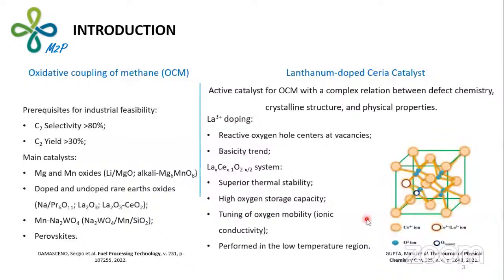The oxidative coupling of methane, the OCM reaction, has some prerequisites for industrial feasibility, such as a C2 selectivity higher than 80% and a C2 yield higher than 30%. In the literature, some catalysts are reported, such as manganese and magnesium oxides, where doping the system with lithium showed the best performance. However, at the OCM temperature, the lithium compound is volatile, and therefore this is an unstable material for OCM conditions.